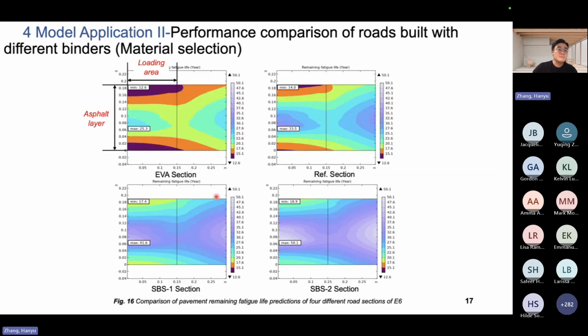Now, the second part of model application is the performance comparison of roads built with different binders. That's mainly for material selection. This figure shows a comparison of pavement remaining fatigue life predictions of 4 trial sections in the same road sections in Sweden. We use different binders, but they are used in the same location. What we see here is that the two polymer-modified binder sections demonstrate outstanding performance when compared to the reference and EVA sections.